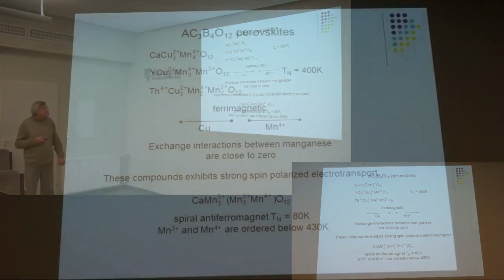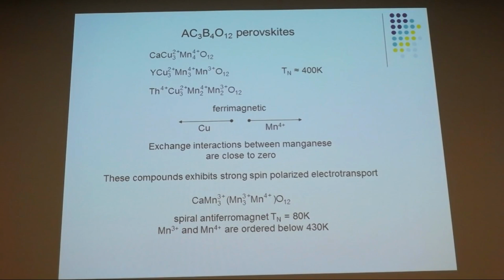This compound is associated with my doctoral dissertation. In Ekaterinburg, Samokhvalov proposed this topic because he believed that the ferromagnetism in this compound arises from double exchange. However, we show that ferromagnetism in this compound arises from antiferromagnetic exchange between copper and manganese. Exchange interaction between manganese ions is close to zero. But these compounds exhibit strong spin polarized electrotransport.